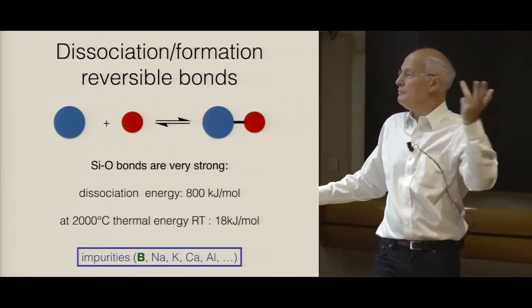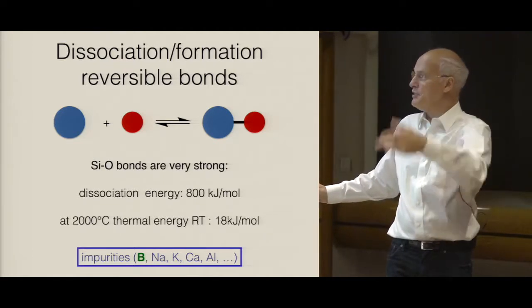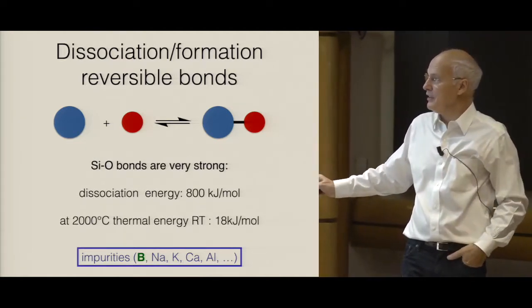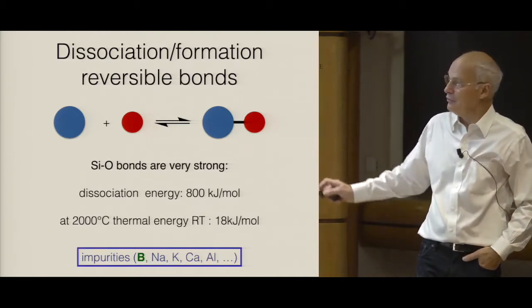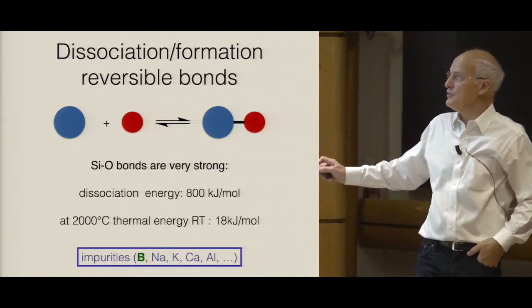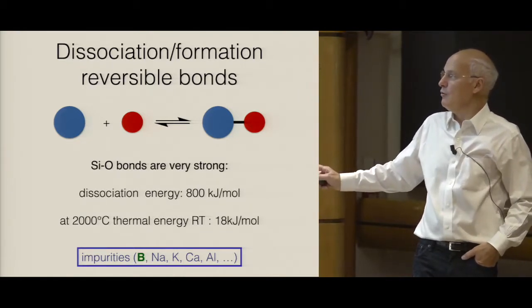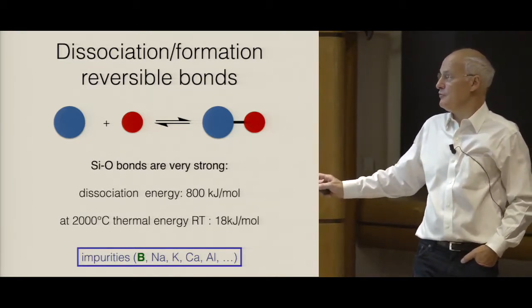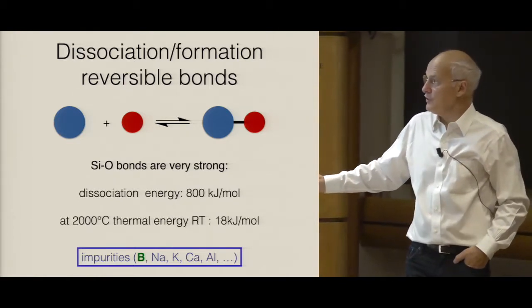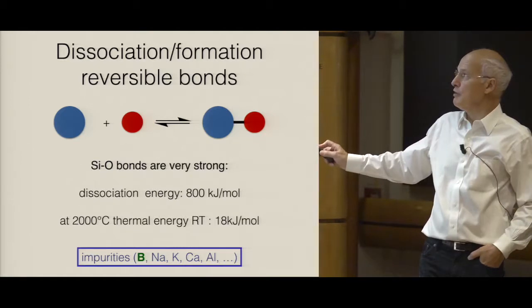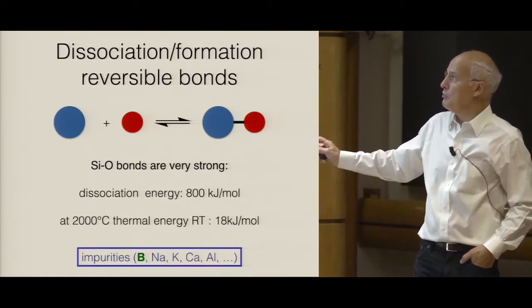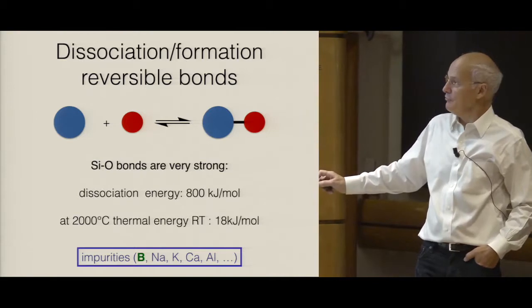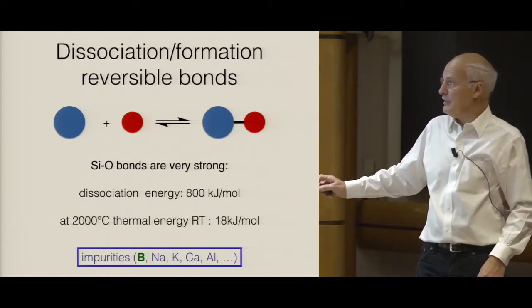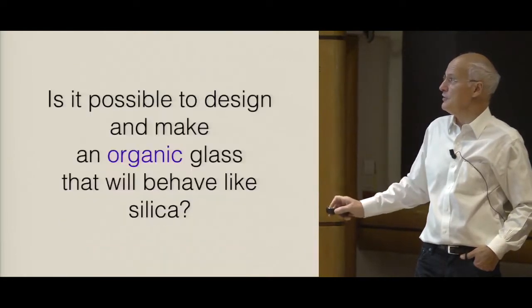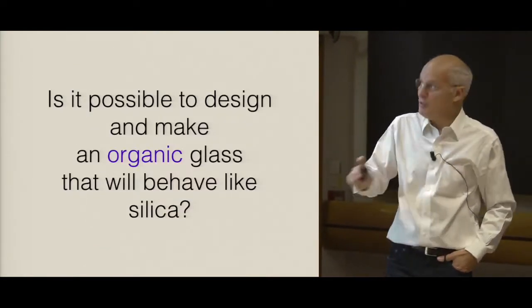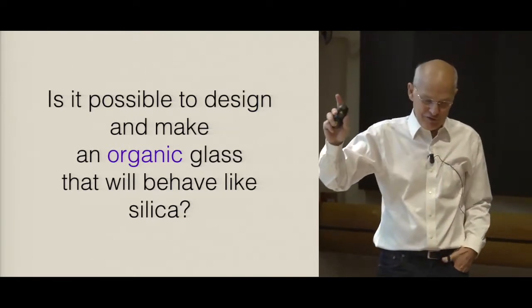And of course, then people say, oh, but there are impurities. We have silicates, so there are alkali atoms, boron, aluminum, and so on. And so this makes the bonds somehow less robust or something like that. I will argue that the impurities are important, but not necessarily for breaking bonds or for going closer to the percolation threshold of this network. They play a role in the kinetics of this system.